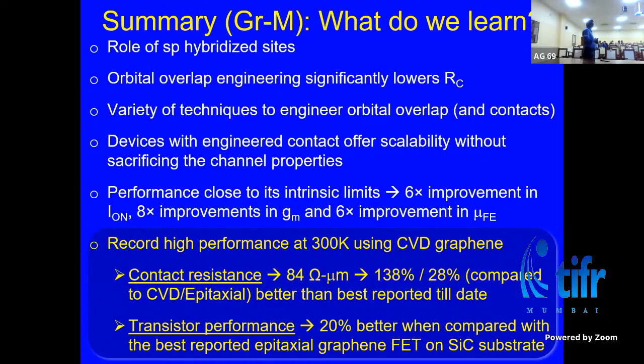So this brings me to the end of my talk. Let me summarize the two threads. On graphene, I talked about the role of sp-hybridized sites. I talked about the orbital overlap engineering, which helps significantly in reducing the contact resistance. And in the case of graphene, I talked about three or four different techniques to engineer contacts, which allow us to improve the scalability and the performance of the device, right? So all the way from contact to the device. If I talk about the contact resistance, we reported record low contact resistance.